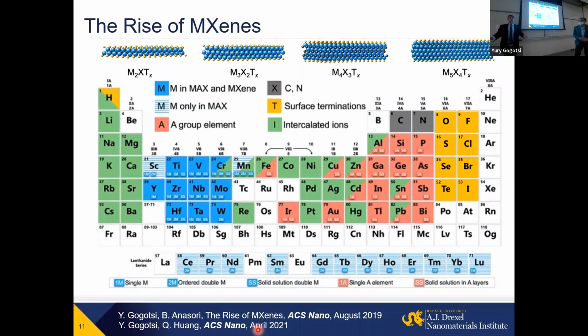If you control them, we can now make titanium 3C2 MXene, the most common, most widely used, about 20%, 1/3 of all MXene publications are on titanium 3C2. Stable as a single flake at room temperature in dilute solution for at least a year. As long as it's in a closed vial in a dark place, it will stay for a year. So again, many problems are solvable, but you need to address them.